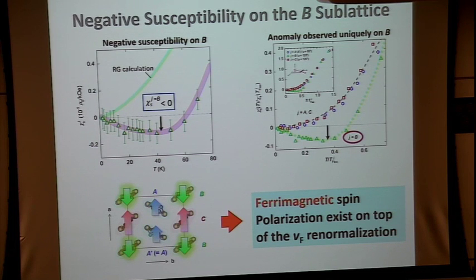It's a paramagnetic state. This means that you apply a magnetic field, and conventionally, all of the spins on average have their moments aligned to the magnetic field. But this experiment suggests that only the B site spin is aligned in the opposite direction. It's very curious. This is a cartoon that shows the experimental data. With the magnetic field applied here, the A spin and the C spin point here, but only the B spins point differently. This is not ordered. This is field induced. So such a ferrimagnetic spin organization is induced by the magnetic field.